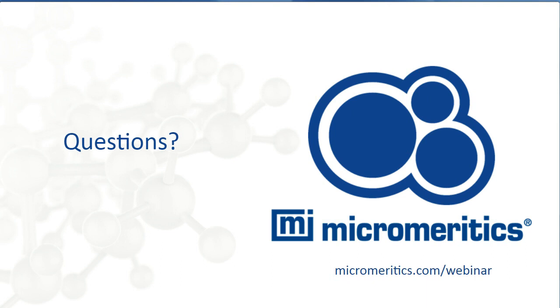Yes, that's a frequently asked question. Think about it this way: if your pores are in the same size range, if the sample doesn't have pores that are too small to be characterized by mercury intrusion or too large to be characterized by gas adsorption, remember I mentioned that overlay. We could overlay the two distributions, and if they don't quite line up, we know quite well that the contact angle between the condensing film of, say, liquid nitrogen or whatever gas we're using for physisorption, it pretty much is zero. There's not much uncertainty there. So the uncertainty is that contact angle that's being used to convert pressure, the mercury intrusion analysis, into a pore diameter. We can adjust the contact angle to get a better overlap of those two.